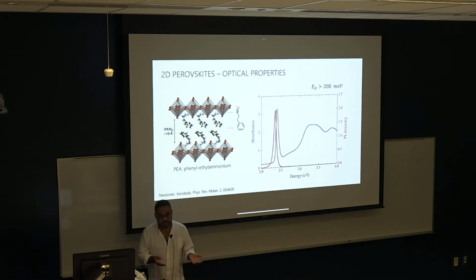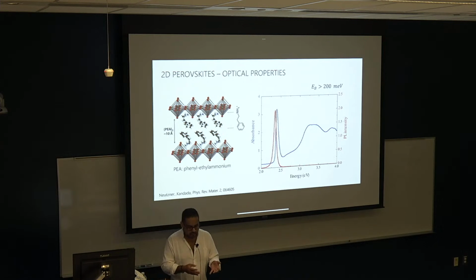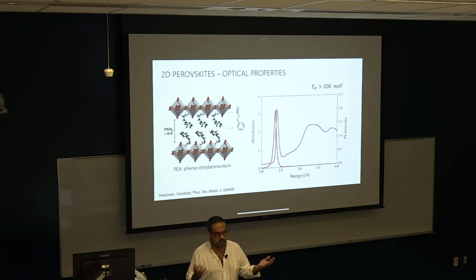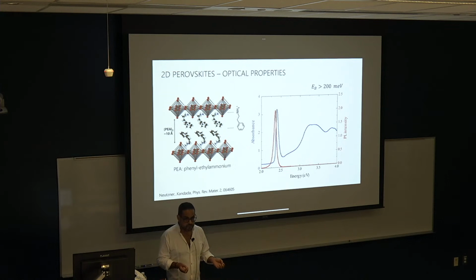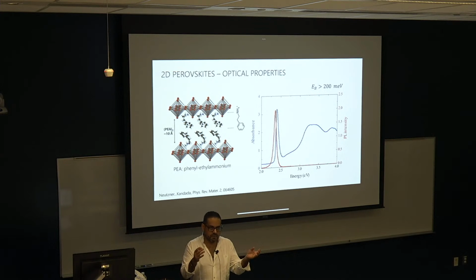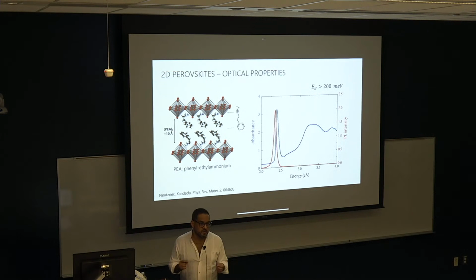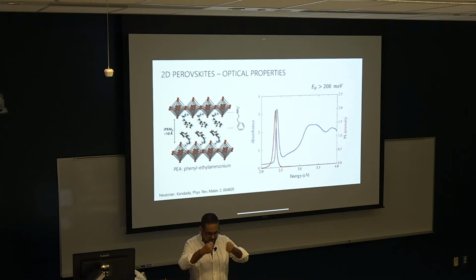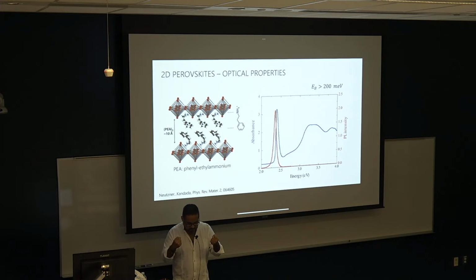In gallium arsenide, for example, in bulk gallium arsenide, exciton binding energies are a few milli-electron volts. You go to quantum wells, very thin quantum wells, and they will go to maybe 16 milli-electron volts. So this is quantum confinement. Electron and hole have very strong interactions, the screening of those interactions is lower, but also there's a quantum confinement. There's a density of states effect in going to 2 dimensions, quantum confinement.